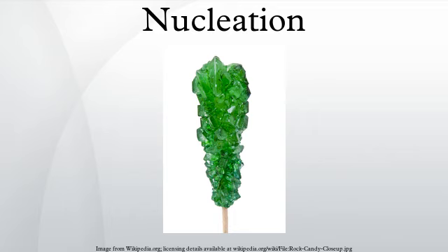The prediction for the rate R is: where ΔG* is the free energy cost of the nucleus at the top of the nucleation barrier, and kBT is the thermal energy, with T the absolute temperature and kB the Boltzmann constant. N is the number of nucleation sites. J is the rate at which molecules attach to the nucleus causing it to grow. Z is what is called the Zeldovich factor. Essentially, the Zeldovich factor is the probability that a nucleus at the top of the barrier will go on to form the new phase, not dissolve.